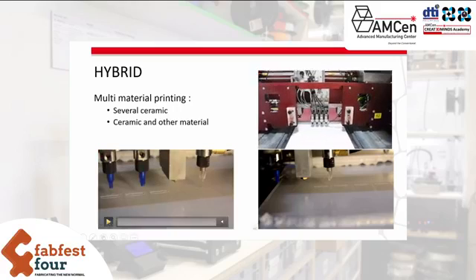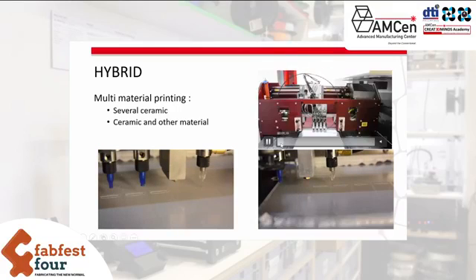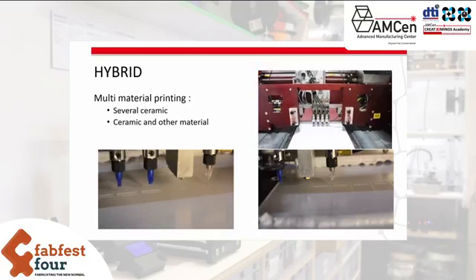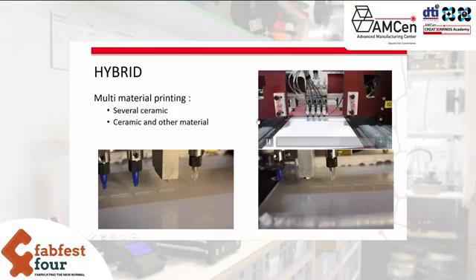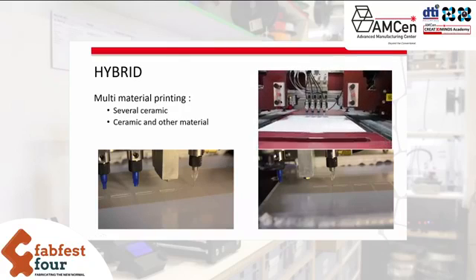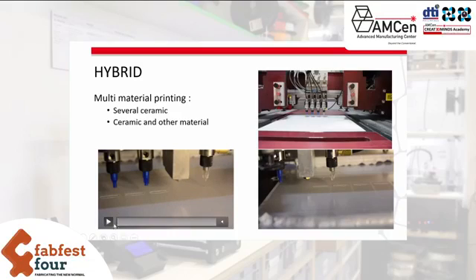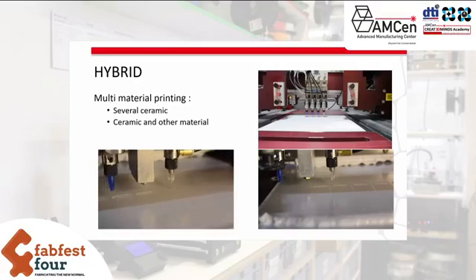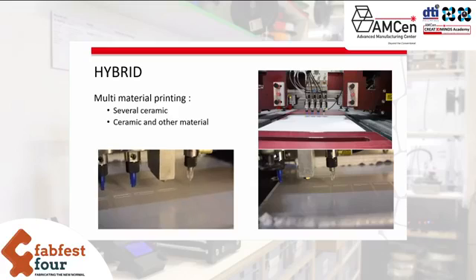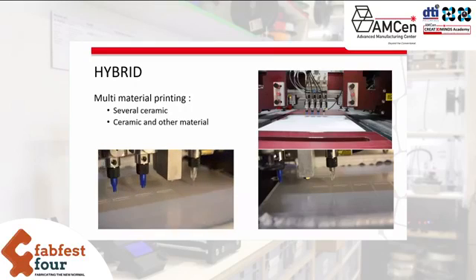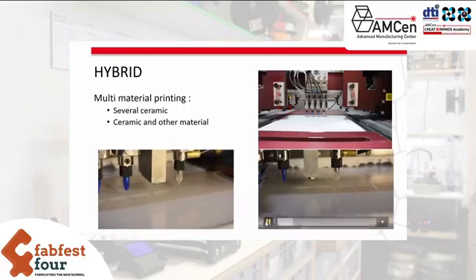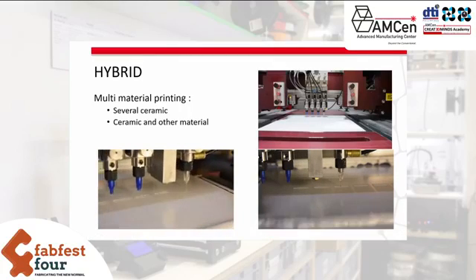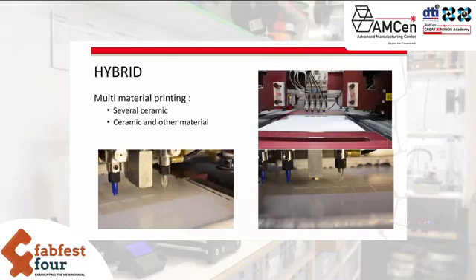So on the top, you can see, as I explained, it is the same printer, okay? And we have a specific scraper on the top with 3 nozzles in order to deposit up to 3 other materials. Then, in the second video, after the scraping and the curing of the ceramic paste, a specific nozzle will come in order to blow compressed air. So it is exactly what you can see on this slide. The specific nozzle blows compressed air, only compressed air at low pressure, in order to remove the uncured slurry on the area where we want to deposit other things. So we blow compressed air in order to create a gap, a groove.